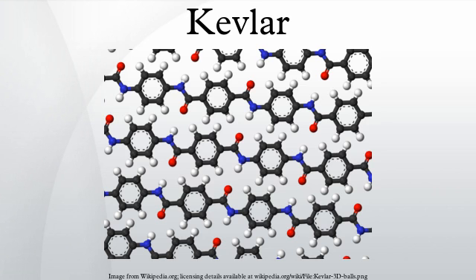Structure and properties. When Kevlar is spun, the resulting fiber has a tensile strength of about 3,620 MPa, and a relative density of 1.44. The polymer owes its high strength to the many interchain bonds. These intermolecular hydrogen bonds form between the carbonyl groups and NH centers. Additional strength is derived from aromatic stacking interactions between adjacent strands. These interactions have a greater influence on Kevlar than the van der Waals interactions and chain length that typically influence the properties of other synthetic polymers and fibers such as Dyneema.